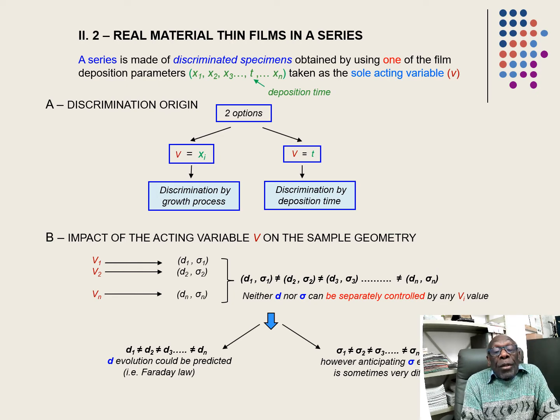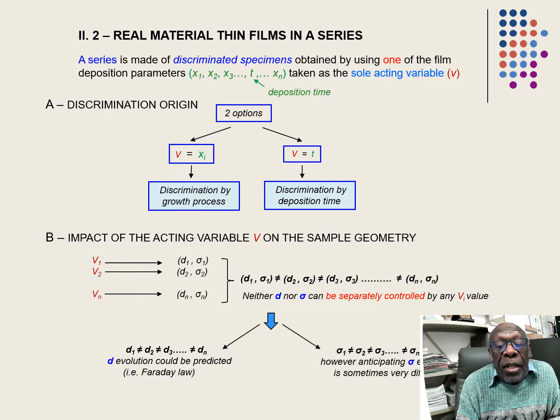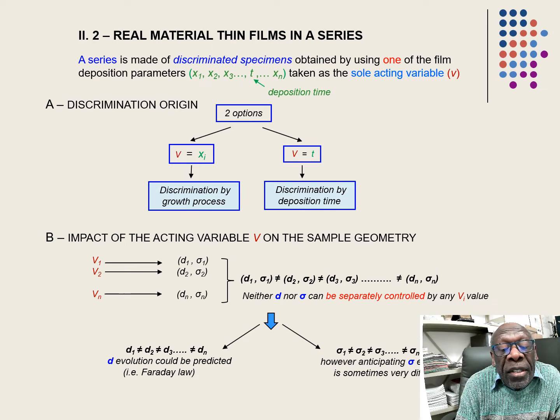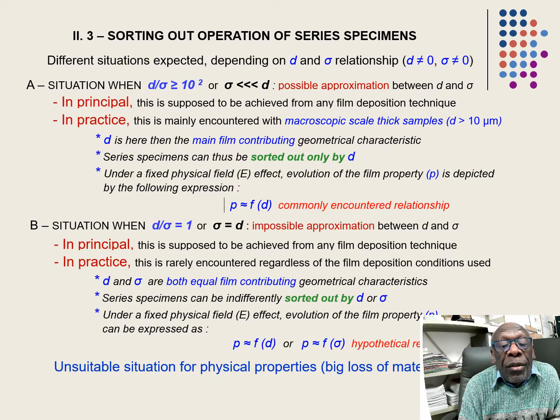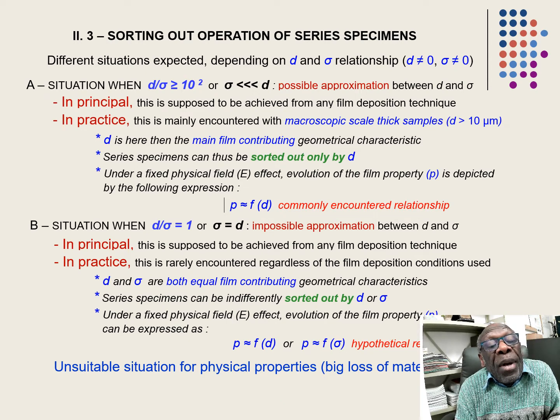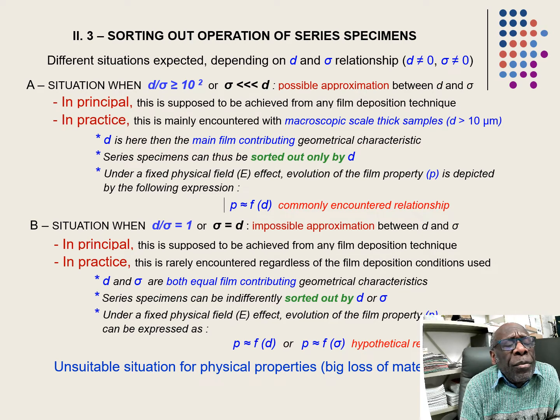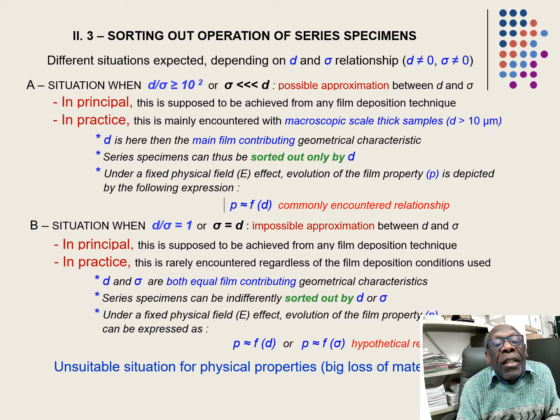So, you should be rational, and for being rational, there is another step. That step is to study the relationship between sigma and D. In that case, you have three situations. When the ratio between the thickness and sigma, the surface roughness, is superior or equal to 10 to 2, that means that you have a sigma which is largely inferior to D. In that case, approximation is possible between the two characteristics.